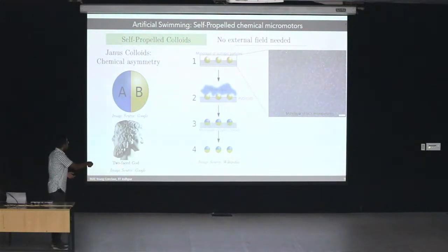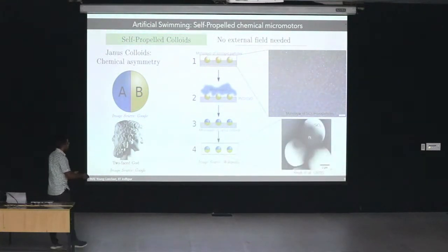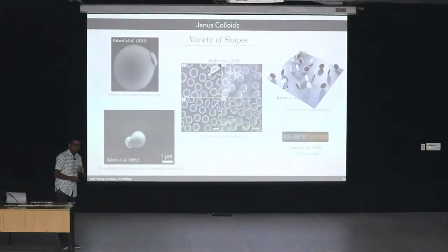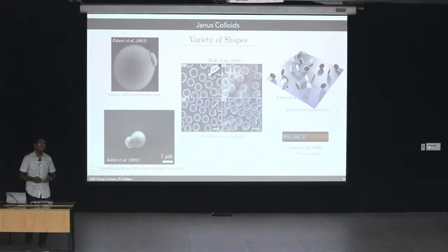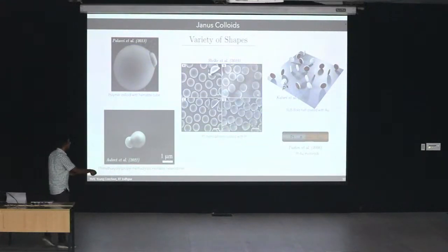And then through physical vapor deposition or CVD, we deposit metal vapor from the top. Now this metal vapor typically could be gold or platinum or palladium. And because of this shadowing effect, only the top half of the hemispheres get coated and the bottom half remains uncoated, and we end up getting very nicely prepared silica platinum or silica gold Janus particles. We don't have to restrict ourselves to spherical Janus particles only. We can create a variety of shapes of Janus particles, such as rod-shaped Janus particles or dimer Janus particles or even disc-shaped Janus particles.